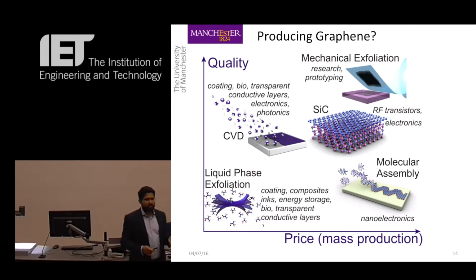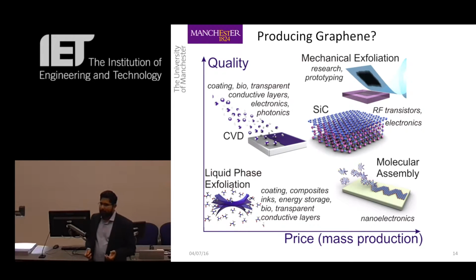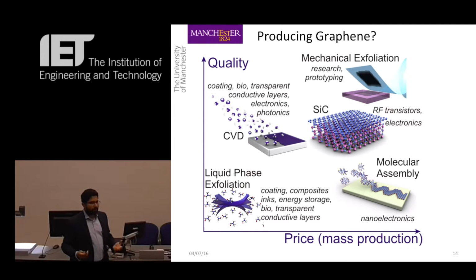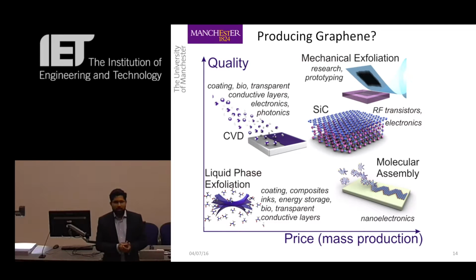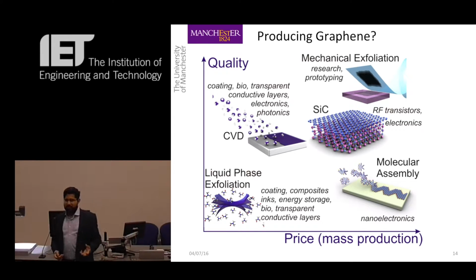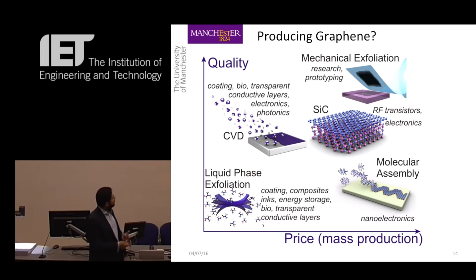But it's not just the price or the quality that determines which graphene you use, it's also the application. If you want to mix the graphene in with a plastic to make an object, you're pretty much only able to use the liquid exfoliated graphene because it's in the right form. You can't use anything else. If you want to coat a surface and make a display, you want a perfect continuous coating of graphene, the chemical vapor deposition is your only option. So very often the technology limits which graphene you select, but in some cases it doesn't, and then the price might be the determining factor.